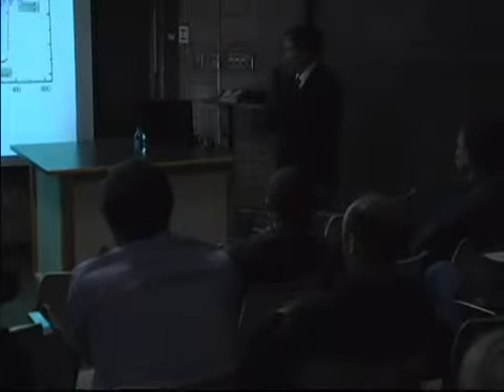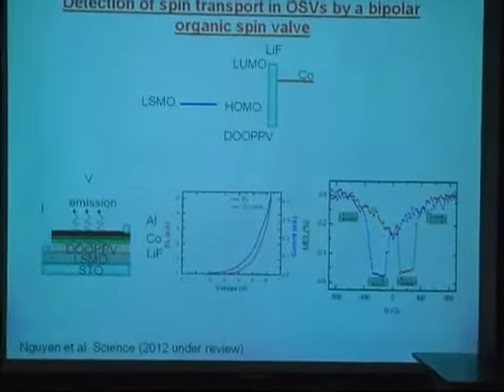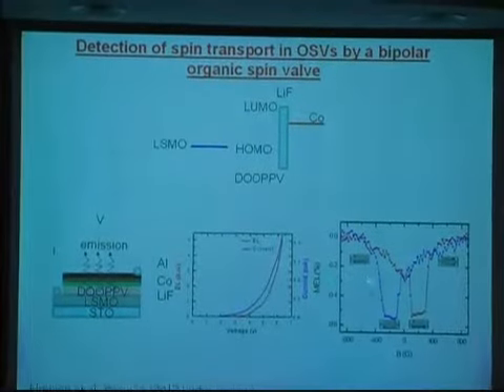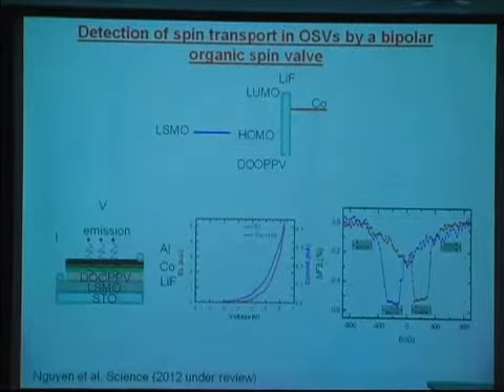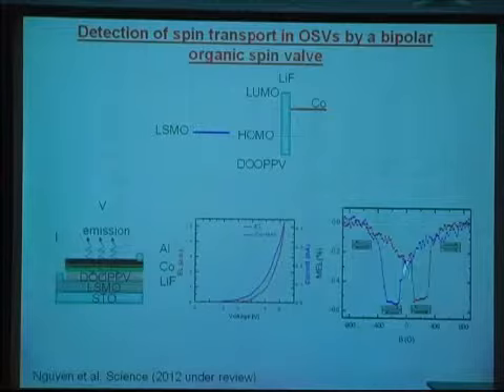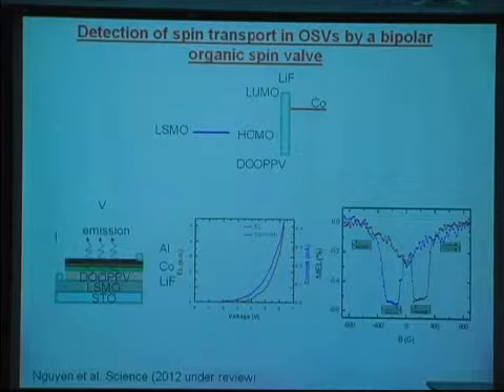Yeah, this is a very good comment. And actually we detect both magnetic field effects on currents and magnetic field effects on electroluminescence, and the magnetic field effect on currents is much less than this. It's about 1 order of magnitude less than this. Yeah. And these are low temperatures. Yeah, this is at 10 kelvins. If we go to 200 or 50 kelvins, the effect is 0.